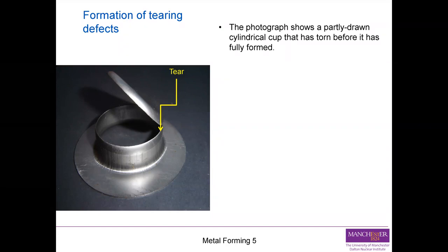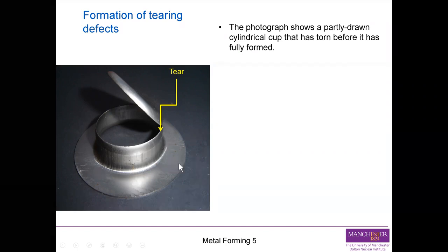In this case, we have a circular sheet of material again, which we try to draw a cup from. And you can see here the end has come off as if somebody cut it using a knife, but this has just happened on its own. It's called tearing. And the problem is the variation in wall thickness. Again, as you see here, we have two situations where around the corner the material has a different thickness than the original material, all the material which is in steady state condition around here.